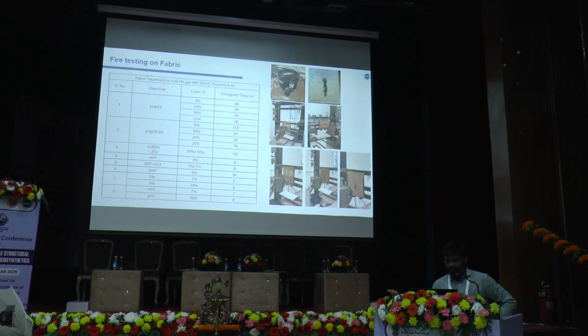This is with the non-woven. You can see it is self-extinguishing immediately after just removing the fire, and not a single spread of flame has been observed. So with that, we considered different kinds of non-halogenated fire retardant, at different weight percentages, and then we checked the extinction time for those, and that combination has been adopted to make the composites.